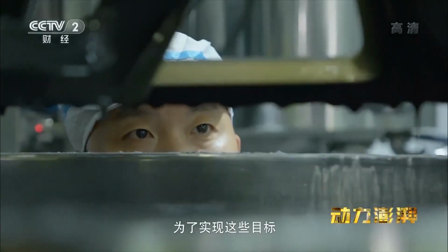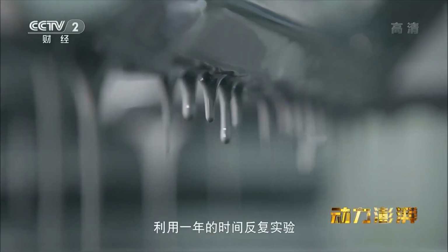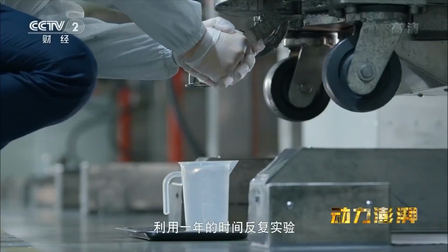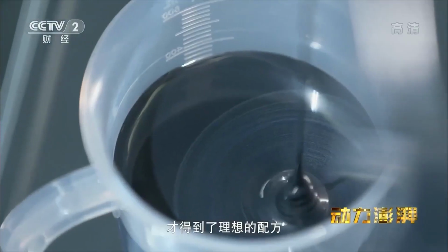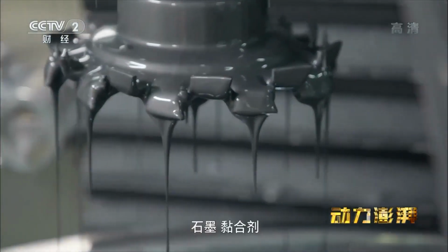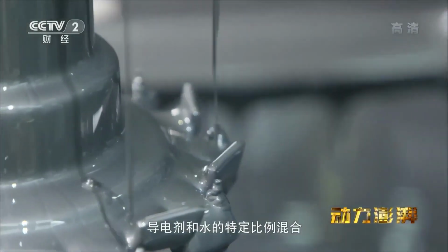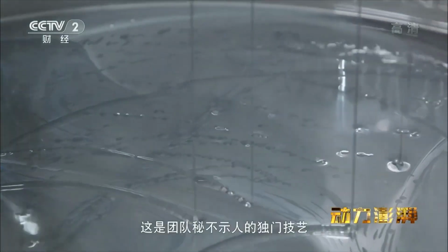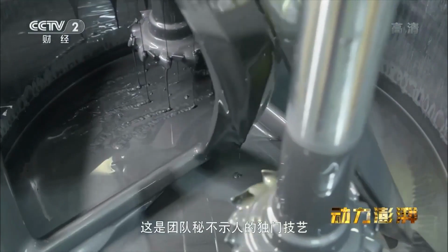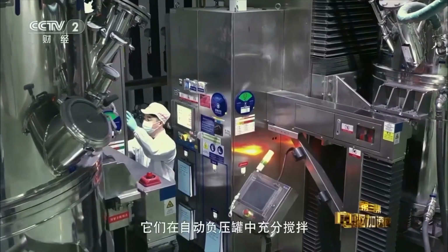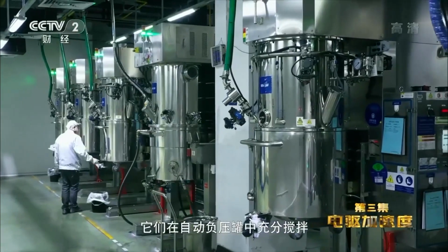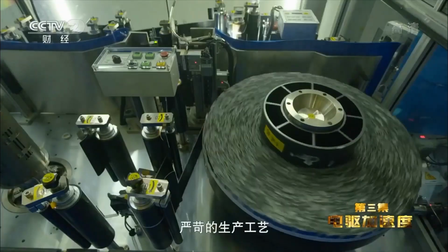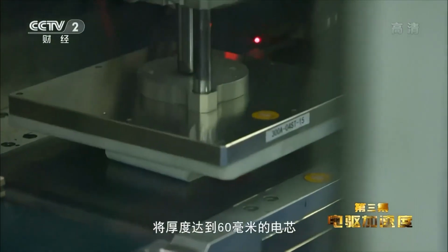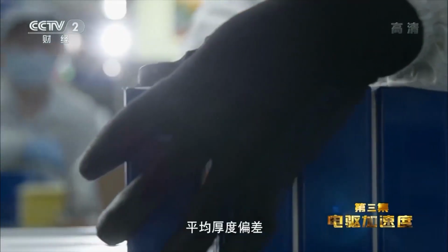In order to achieve these goals, Wang Shengwei and his team used a year of trial and error to get the ideal formula. The mixing of graphite, binder, conductive agent and water in specific proportions is a secret technique of the team. They are fully stirred in an automatic negative pressure tank and will be applied to the copper foil after mixing well. The production process strictly controls the average thickness deviation within 0.1 micrometers for a thickness of 60 micrometers of cells.